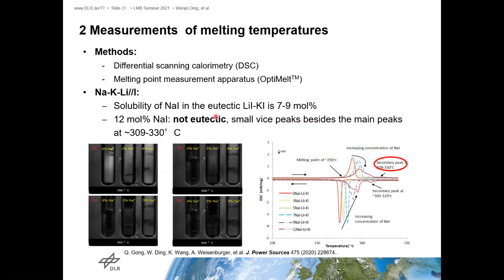After the simulation, we use DSC and a calorimeter as methods to measure the melting temperatures. The measurement finds the solubility of sodium iodide is about 7 to 9 mol%. It's lower than the simulated values. If it contains 12 mol%, in the DSC we can find a second peak, and that means there is some solid salt inside. It cannot be used for the liquid metal battery if the operating temperature is in this range.